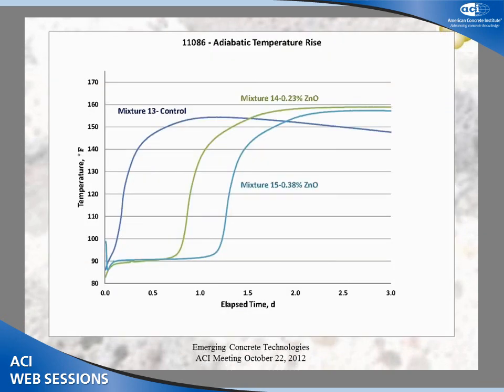So based on that work, three mixes were selected for the adiabatic heat of hydration. And this is basically what we saw. The control mixture, mixture number 13, contained no zinc oxide. Mixture 14 had 0.23% zinc oxide. Mixture 15 had 0.38%. And the actual heat of hydration was about the same.